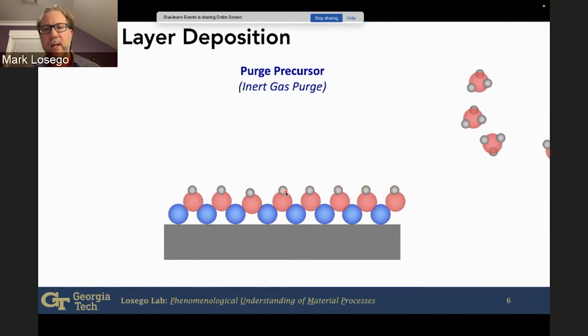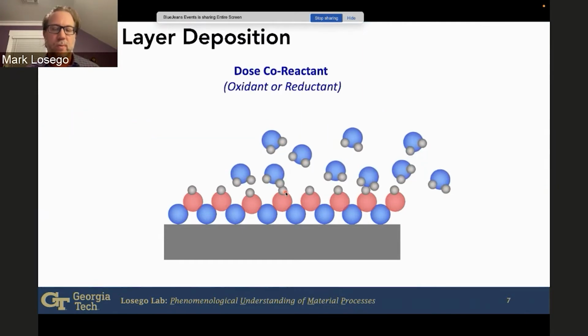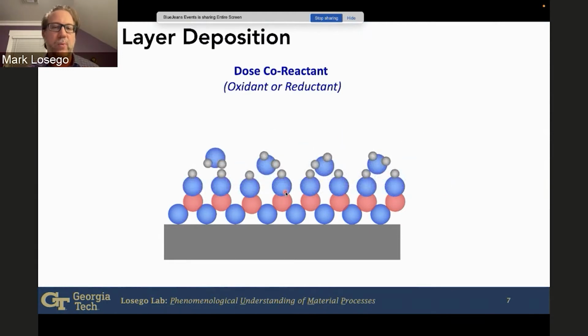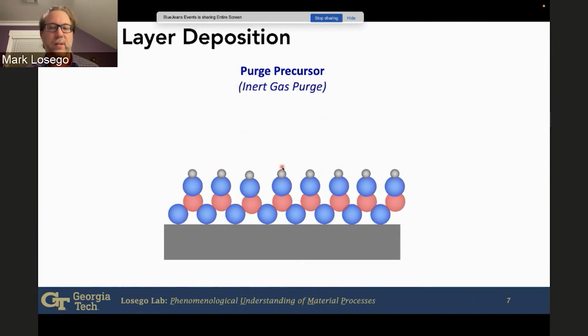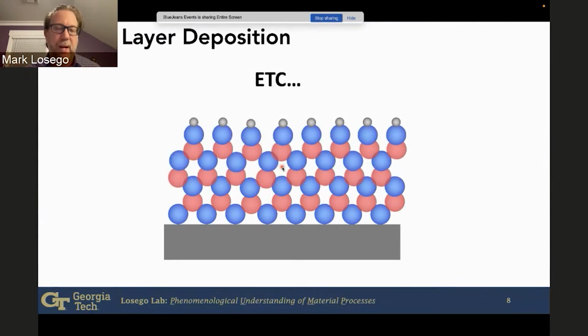And so we can then purge off any excess, leaving just a single atomic layer of material on the surface. We can then come in with what we call a co-reactant, another gaseous species that can again react with the surface chemistry that's available but not react with itself, such that we get self-limited termination of the atomic layer that we put on that surface. We can then bring in these red atoms again and repeat this over and over until we build up, atomic layer by atomic layer, the coating that we want on the surface.